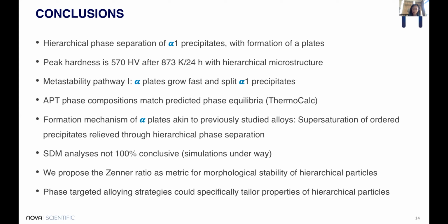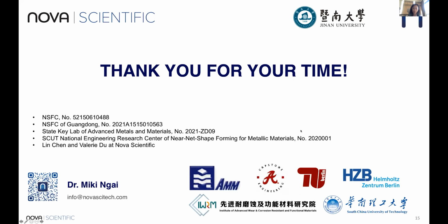Atom probe phase composition matches predicted phase equilibria. The formation mechanism of alpha plates is akin to previously studied alloys. Supersaturation of ordered precipitates is relieved through hierarchical phase separation. Spatial distribution map analyses are not 100% conclusive. We propose the Zener ratio as a metric for morphological stability of hierarchical particles. Phase-targeted alloying strategies could specifically tailor properties of hierarchical particles. And thank you very much for your attention and time.